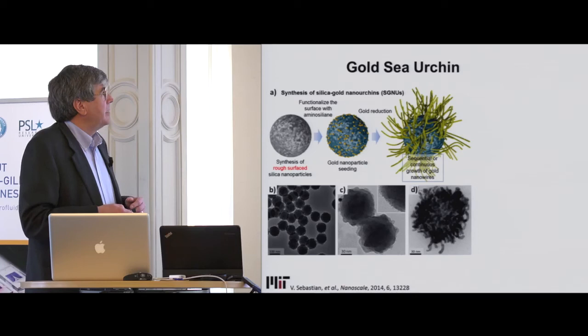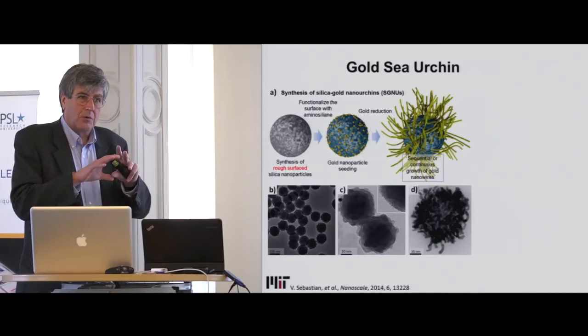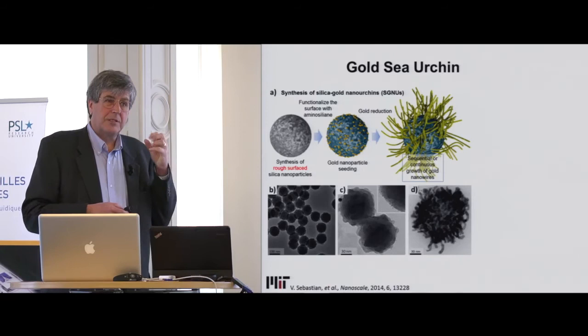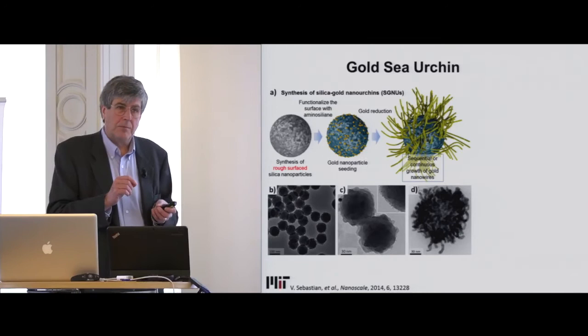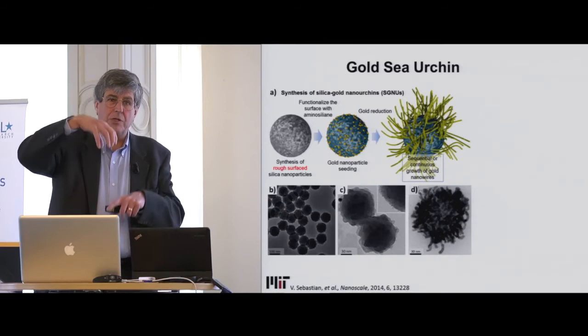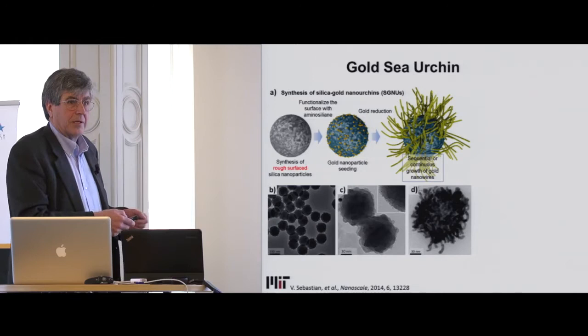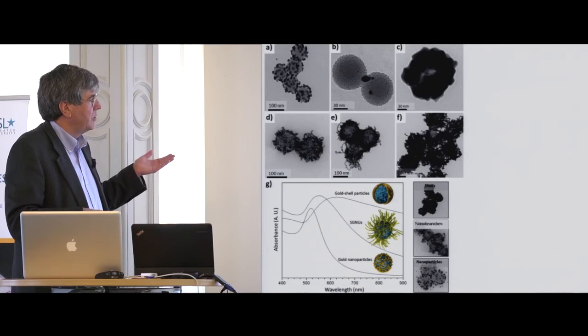One final example of nanoparticle synthesis: if we take silica spheres but make them rough instead of smooth, then nucleate gold nanoparticles on them, we can control the nucleation and transport to the particle so it's much more advantageous for the gold to grow on top of the rough peaks as opposed to down in the valleys. What actually happens is you starve the nanoparticles in the hollows relative to the ones on top, and as a result you grow very long strings of nanoparticles off the side — giving you these sea-urchin structures of nanoparticles. You can do this in microfluidic systems and carefully control where you are in the whole growth region, controlling the emissions. You can then use the same kind of self-assembly of these nanoparticles to make three-dimensional structures for surface-enhanced Raman spectroscopy by impregnating them with the material you want to study.